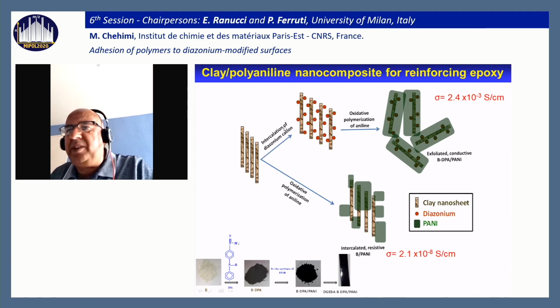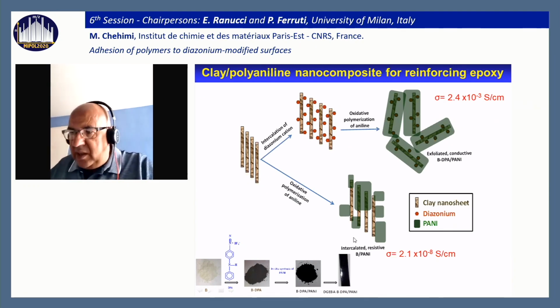Two things may happen. When we use the diazonium salt, we intercalate the clay and make clay polymer nanocomposites with some percolation here, and we obtain a high electrical conductivity, 5 orders of magnitude higher than the clay polyaniline nanocomposite without any pre-intercalation with the diazonium salt. So the diazonium salt here permits not only to intercalate the clay, but to make a conductive path of the polyaniline in the clay polyaniline network.